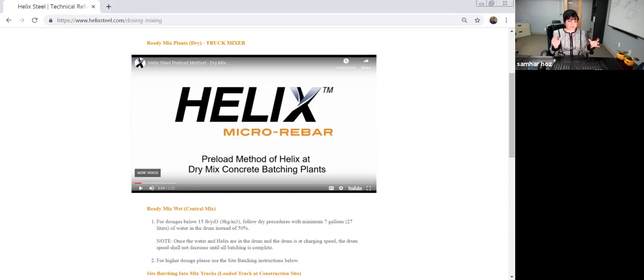Just in general, Helix will be shipped in 45-pound boxes. So all they need to do is just dump the boxes in, and add the water first. Anything more than 50% of the batch water first. Mix for 45 seconds and then go back to the normal manner of mixing.